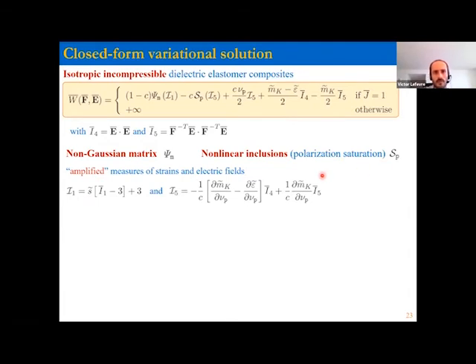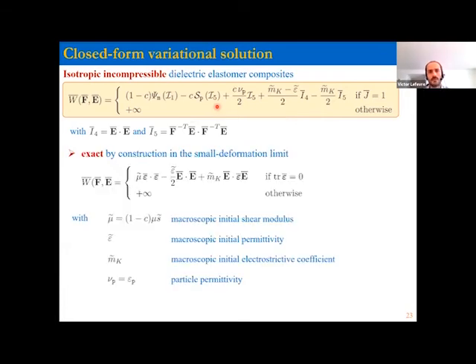So in there we have these amplified measures of strains and electric field, script I1 and script I5. What's important really is that by construction, it's exact in the small deformation limit. That's the formula it reduces to. You can see here mu tilde is the macroscopic initial shear modulus, epsilon tilde is the macroscopic initial permittivity, and m tilde k is the macroscopic initial electrostrictive coefficient.